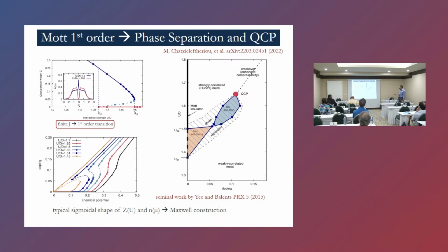phase diagram over here, which then really is the final shape of the phase diagram at the end of the doped phase, where you have this metallic phase, which is connected to the half-filled metal, which then undergoes a first-order transition not to the Mott insulator, but to another metallic phase, which is instead adiabatically connected to the Mott insulator at half filling. And these are intercalated between these two phases. There is a zone of phase separation that ends in a quantum critical point. And then you have a crossover.